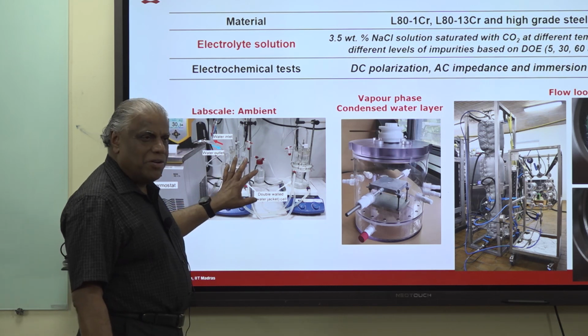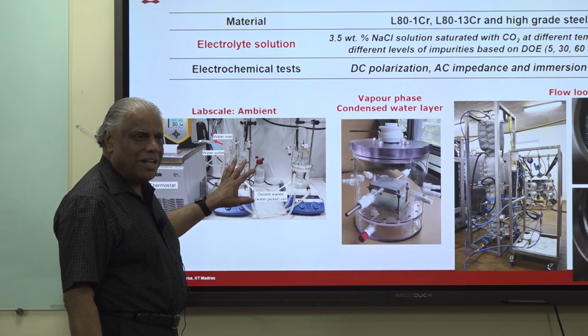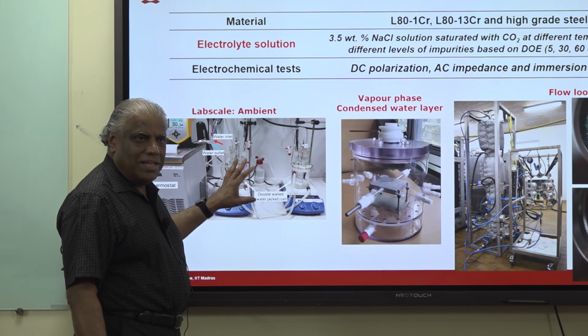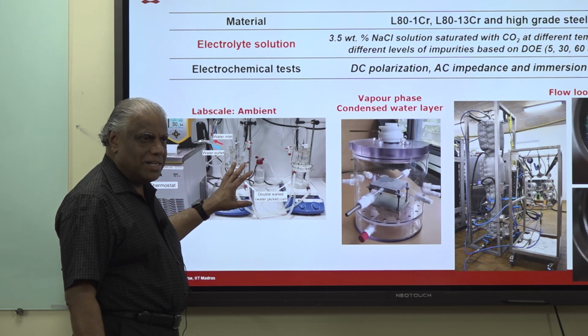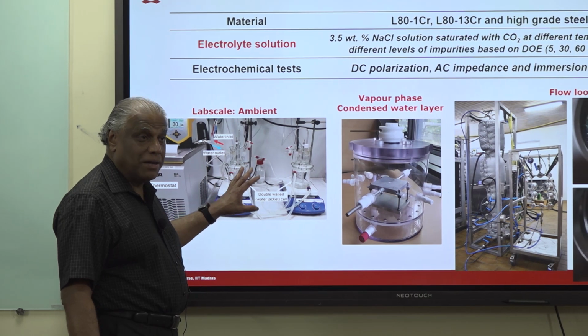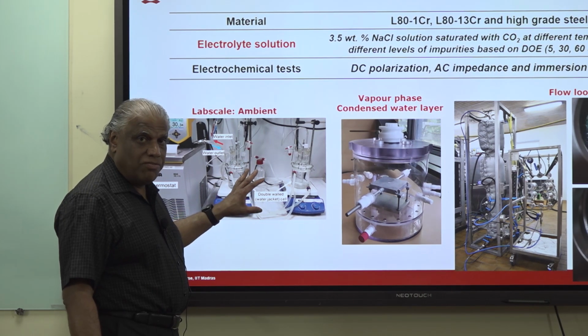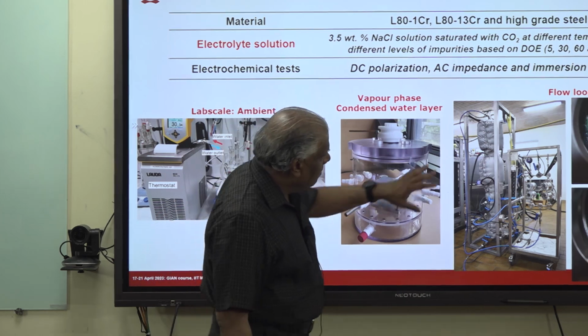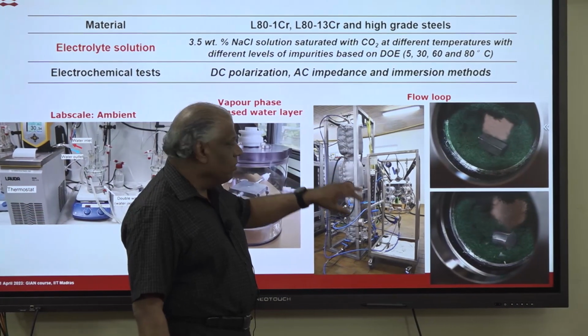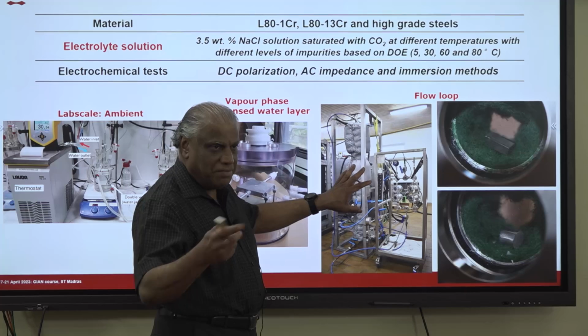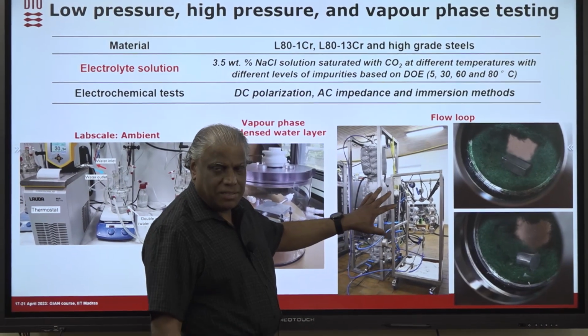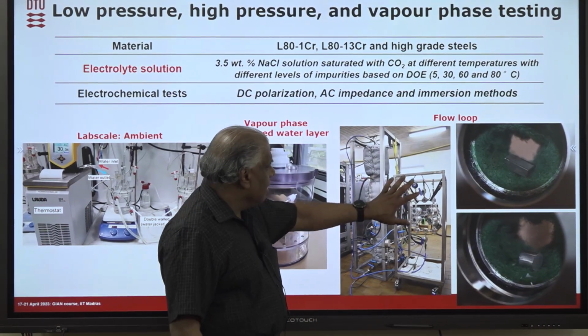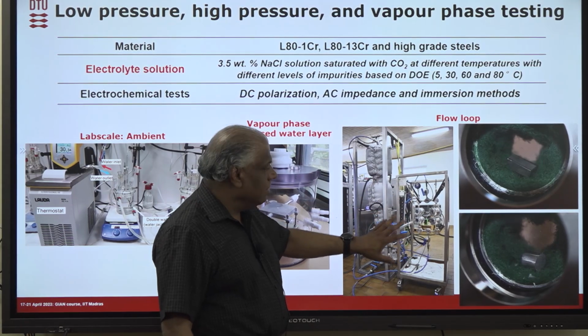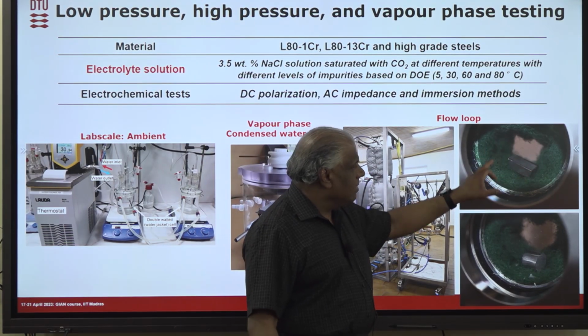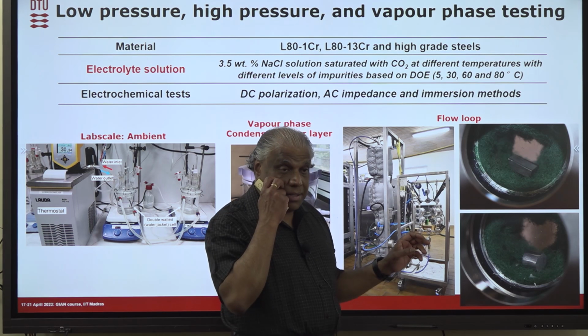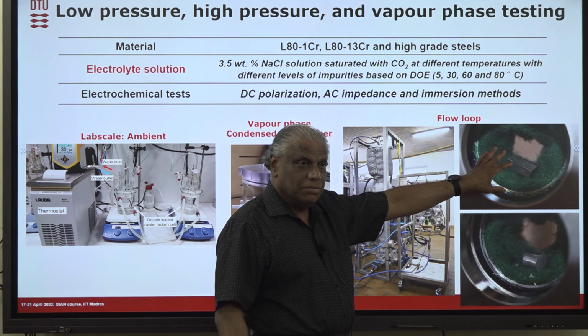But this experiment will not give us a total idea, right? Because this is at atmospheric pressure. But when the supercritical CO2 is injected, the pressure is probably 300 bar, and it is in a supercritical form. So we use the flow loop experiment. We collaborate with a company that has a flow loop, and there we can get actual 300 bar pressure, and inside these chambers you can get supercritical CO2.